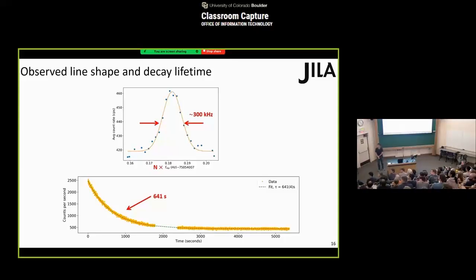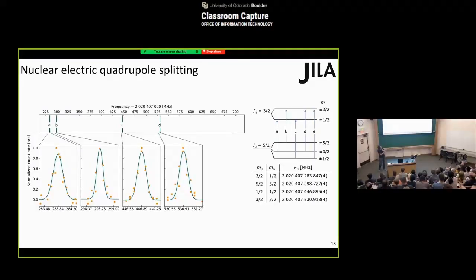You mentioned the Earth's magnetic field, so you have a Zeeman effect. How sensitive are you to magnetic field changes? Could you do some form of magnetic resonance spectroscopy and probe chemical processes, crystal field effects, or effects of defects in the crystals you embed the thorium in? Since we're dealing with a nuclear transition, it's just the nuclear alignment to the magnetic field, so it's about a kilohertz per Gauss through the nuclear magneton. Can we do some magnetic type of spectroscopy? We can, essentially with these different quadrupole moments. You can imagine putting in a microwave and driving the transition between these different M states, different alignments of the quadrupole inside the electric field gradient, by coupling to the nuclear magnetic moment.